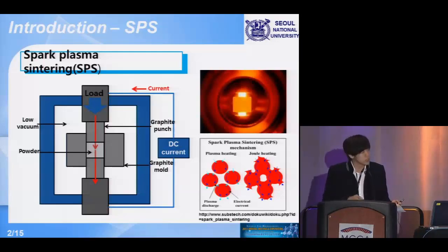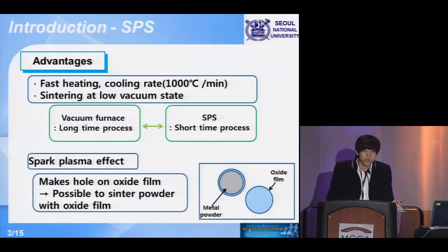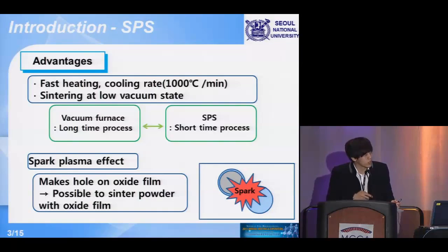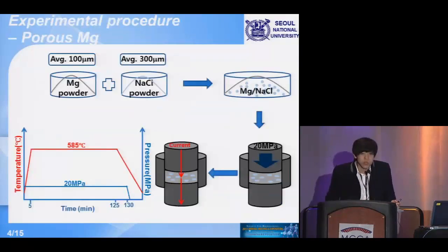And it makes the sintering start. There are some advantages of this SPS, such as fast heating and cooling rates are possible, and the sintering occurs in a considerably low vacuum state. So it has a shorter process time compared with the general vacuum furnace. And the more important aspect is that sparks occur between the powders, which destroy the oxide film on the powders and help the sintering occur. So this is a brief design of the experimental procedure of my work.